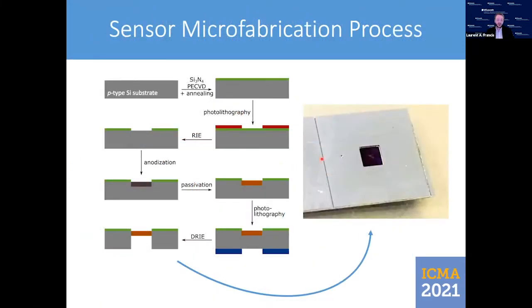Now let us detail the full fabrication process. Porous silicon anodization is compatible with standard microfabrication techniques. In order to define the porous area, a silicon nitride mask is deposited on a highly doped p-type silicon wafer. Then we use photolithography and reactive ion etching to create a pattern of the area where we want to have the porous silicon itself. Then we have an anodization to create the porous silicon, which is then passivated using thermal oxidation. And then to open the porous layer, a thick resist mask is coated and patterned using photolithography again, serving as mask during the deep reactive ion etching of the back of the wafer.